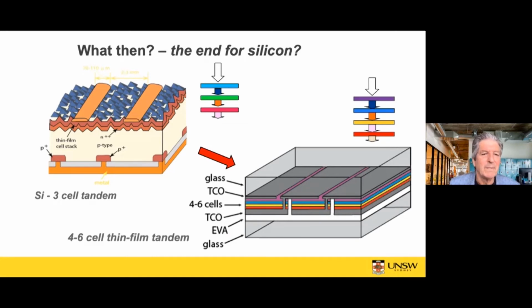So stacking one cell onto silicon definitely makes sense. You get a big boost in performance. The second cell you stack onto silicon comes at very little extra cost. But each time you stack a cell onto silicon, you share the available photons between all the cells. So with a 3-cell stack, silicon is only seeing 1/3 of its normal photon count, so its power contribution to the stack goes down to 1/3 of what it would be. So if you go to a 4-cell stack, the silicon contribution would be going down to 1/4 of what it normally is, and you just wonder if the silicon was really required. By then, the materials that we're stacking onto silicon would be well validated. So my prognosis is that the first 4-cell stack will be an all thin film tandem using whatever technology ticks all those 4 boxes that I mentioned previously.